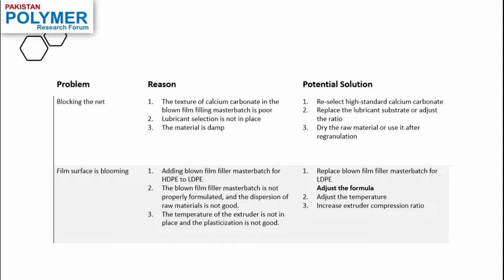And the practical reasons behind the blooming of the film can be that you're actually using the wrong type of film master batch for the wrong type of resin. For example, you have manufactured a polymer master batch for HDPE, and you're using it for LDPE resin. So there will be a difference in the melting points of both the master batch and the resin, and you'll get the high melting material blooming to the surface of this film.